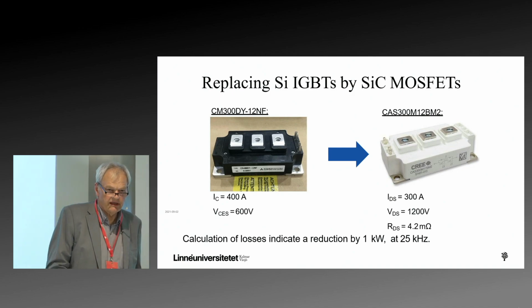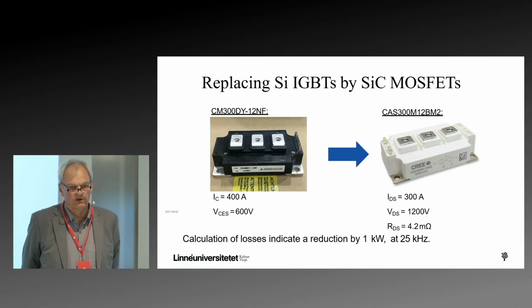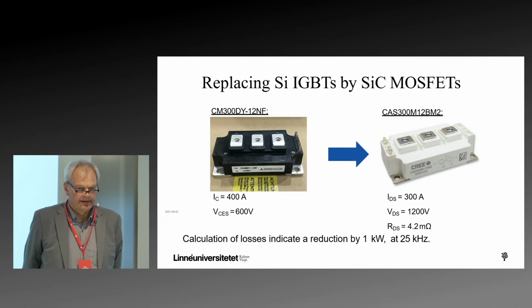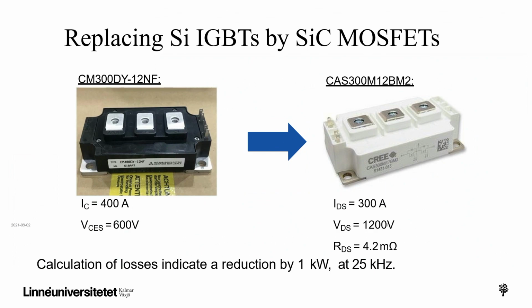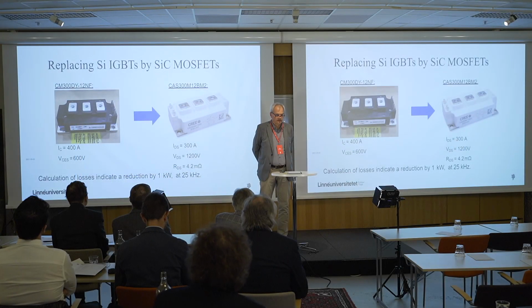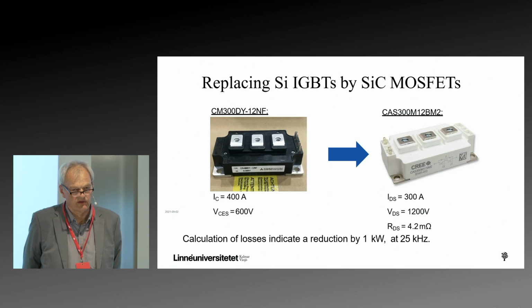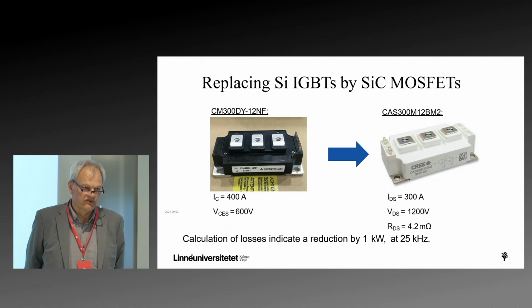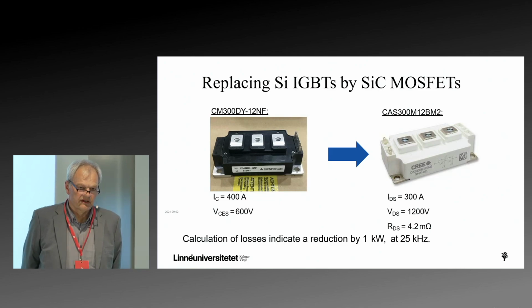So here we have a first test we did on what SiC MOSFETs will bring. We had roughly 2.7 kilowatts from the silicon IGBTs, and we could reduce the losses of the switches by roughly 1 kilowatt. But if you try to calculate the losses you would expect in the SiC MOSFETs, this is way more. Might be 3 times the expected value. So there is still more than 1 kilowatt of switching losses, which you shouldn't have in a SiC MOSFET.